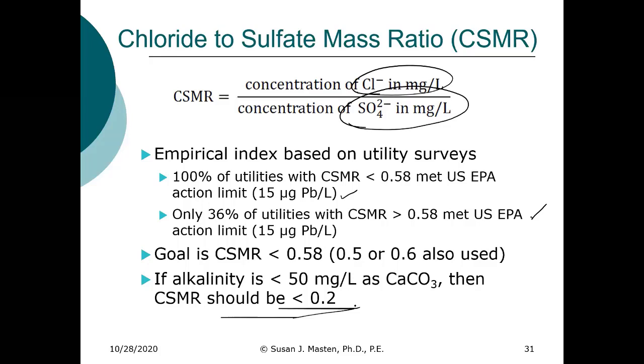Just to give you an example, in Flint, after treatment, the CSMR in Flint ranged from about 2.5 to 3.2. So a significant increase in the CSMR. That was because of the ferric chloride that was added, which releases 3 moles of chloride for every mole of ferric chloride that's added.